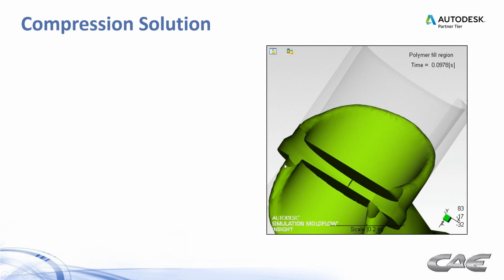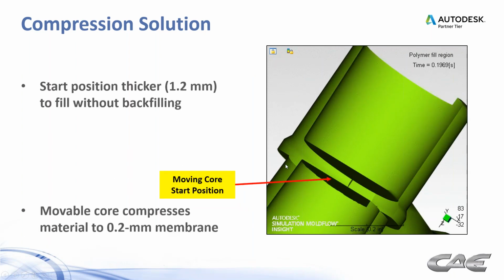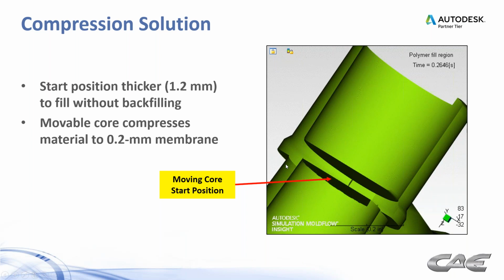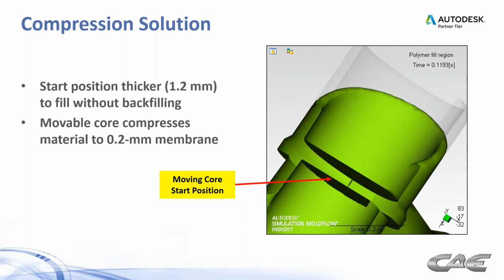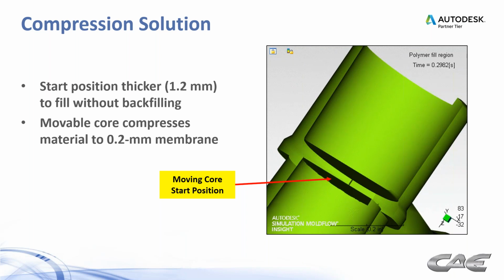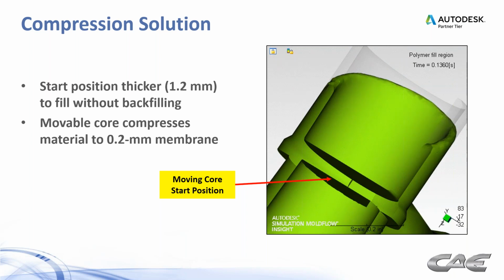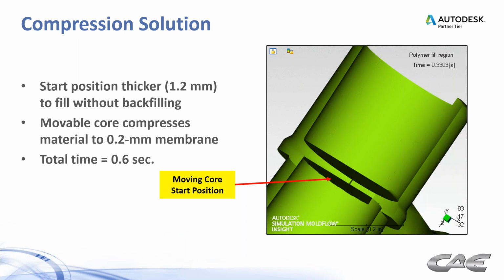And then what you see here, you'll see in a second this core will start to move. So we actually have the ability to simulate that movement of the core, fill it first, and then compress it in a very short period of time so that area doesn't freeze off quickly and end up with that 0.2 millimeter membrane. So very, very unique way to achieve thinner walls. And the total time to do all that, inject and compress, was on the order of 0.6 seconds.